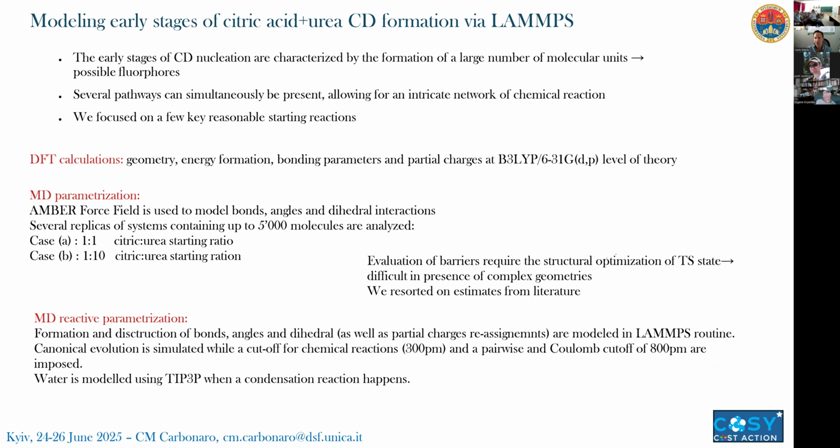So we are using some evaluation of the barrier required to get into those geometries. We need to consider some of the possible reactions that could happen during our synthesis, of course, and we are using a sort of reactive molecular dynamics in the presence of water, which was modeled by TIP3P during the synthesis.